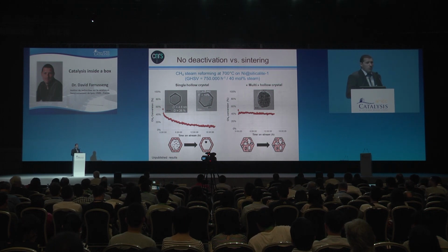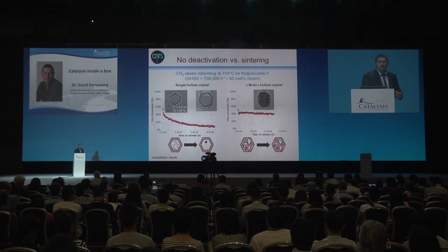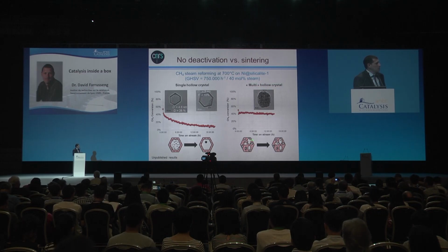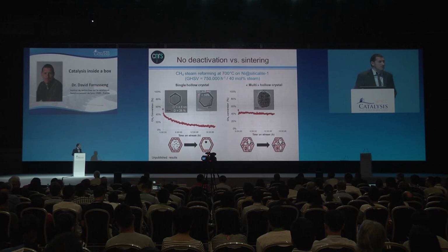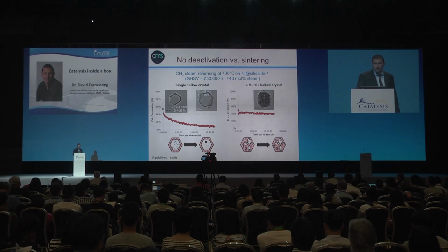So a way to prevent that is to make small cavities, multi-hollow catalysts, multi-hollow cavities, so that all the nickel particles are really encapsulated and then cannot really sinter, or not sinter so much. And you can see here the stability is well maintained for a day.